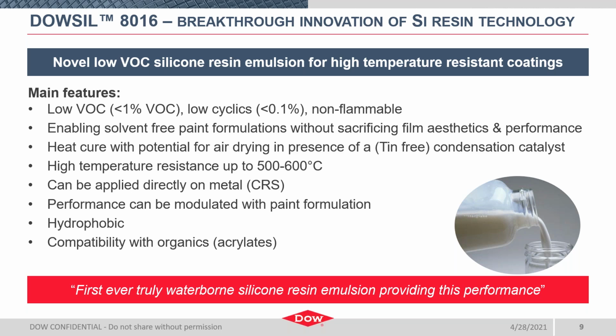And more uniquely to 8016 is its compatibility with organic co-binders such as acrylates, which can be blended in for light to medium duty applications that only require moderate temperature resistance. The formulation flexibility is going to enable formulators to dial in on specific performances. In our 2020 launch of 8016, we had initial indications of this compatibility and potential for a broader range of coating performances, but we didn't really have in-depth data to share at that time. So since that initial launch, we've dug deeper into this, and I'm going to highlight some of the data collected on these systems towards the end of this webinar.